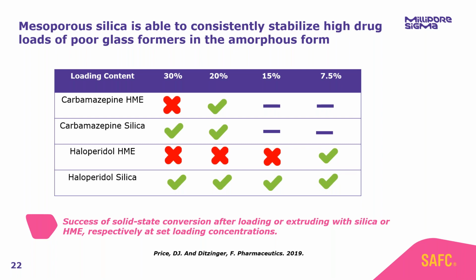Straight away off the bat, we observed that mesoporous silica was able to consistently stabilize high drug loads, whereas HME was unable to do so. Carbamazepine HME was crystalline at 30% drug loads. We were only able to stabilize 20% drug loads in a carbamazepine hot melt extrusion. However, for carbamazepine mesoporous silica formulations, we were successful at 30%. For haloperidol, the situation was even more dire, shall we say. We were only able to stabilize 7.5% drug load in the amorphous form in hot melt extrusion, whereas mesoporous silica was successful in stabilizing 30% drug loads of haloperidol.